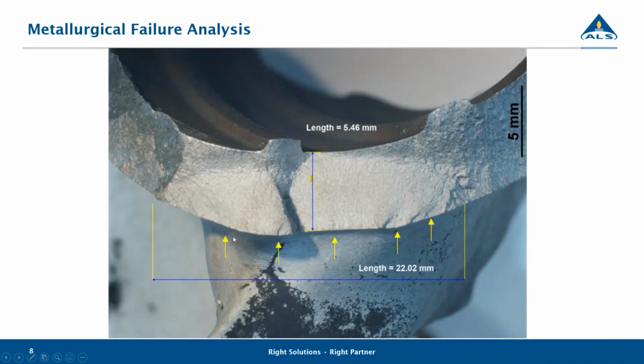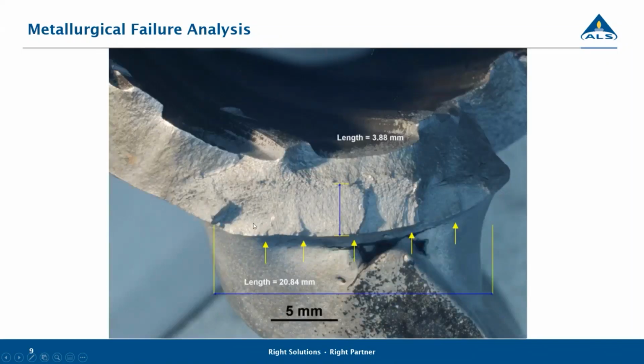You can also see ratchet marks from the fatigue, and the fatigue crack grew from this area almost all the way through. This is the other side. There you can see the ratchet marks a little bit clearer, and it also didn't grow all the way through. And this was at about 3.88 before the tube let go. You can also see here what the weld geometry looks like. So the bracket is basically unprepped, just welded on both sides, and there's no weld at the top.